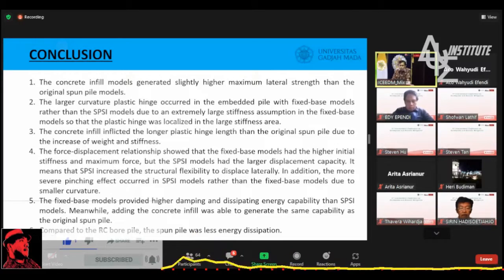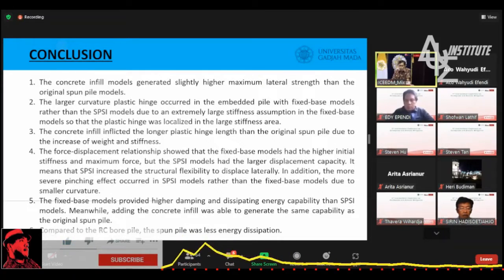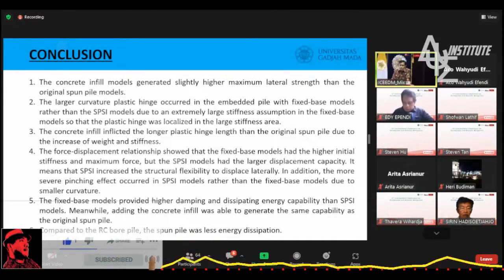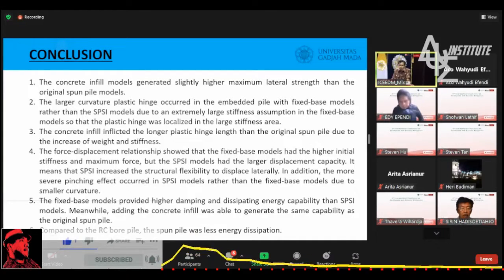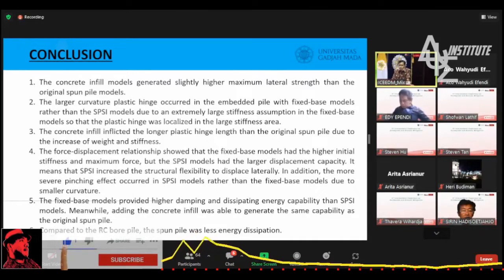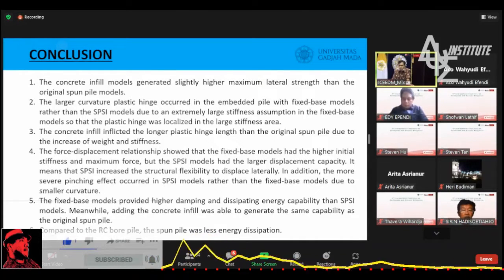The force displacement relationship shows that the fixed base model had the higher initial stiffness and maximum force, but the SPSI model had the larger displacement capacity. It means that SPSI increased the structural flexibility to displace laterally.